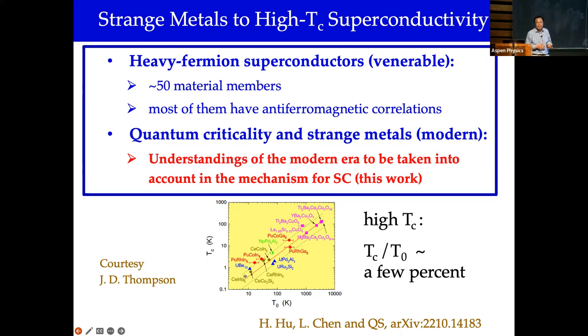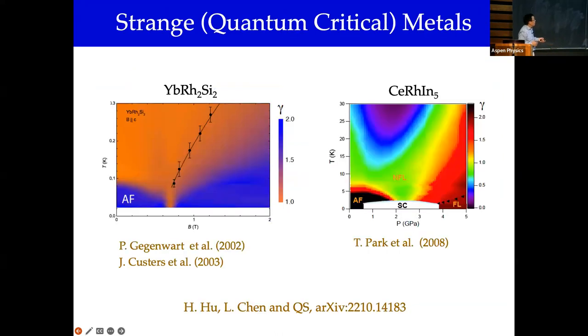If you look at this color scheme here, the green means this label gamma, that shows the resistivity versus temperature. I was trying to say that if you have quasiparticles, the resistivity versus temperature, there's enough umklapp scattering. As a result, it would reflect the scattering rate, which is T squared. For instance, various regions here have T-squared dependence: here in the blue region, here in the black region, what's labeled as Fermi liquid. But when you go to some special regions, in this diagram of temperature and pressure, you see this T-linear resistivity. And likewise here, temperature and, in some cases, magnetic field, which is tuning.